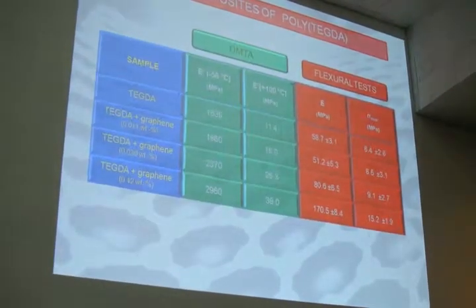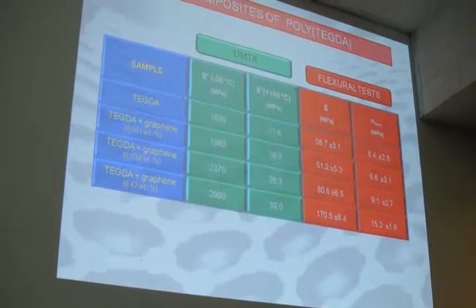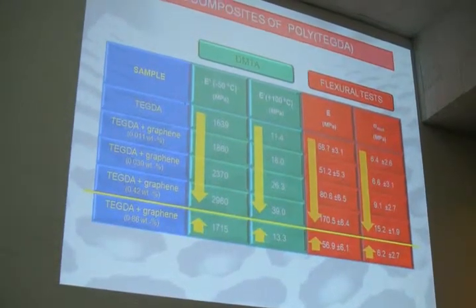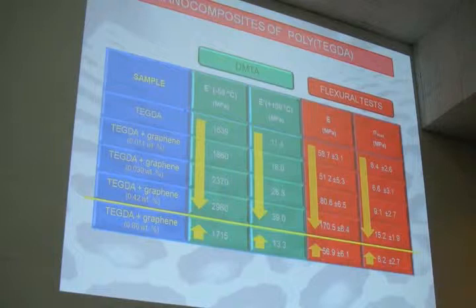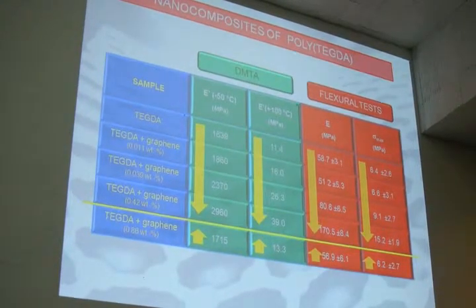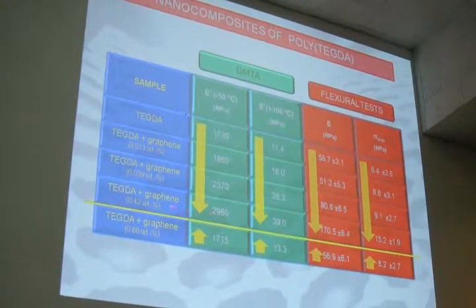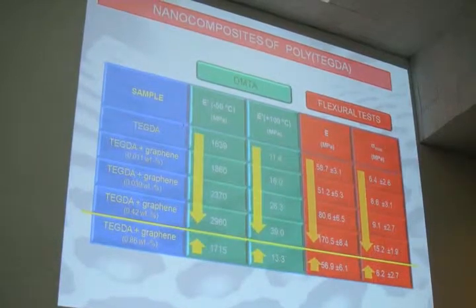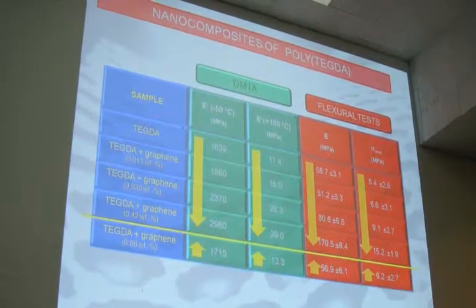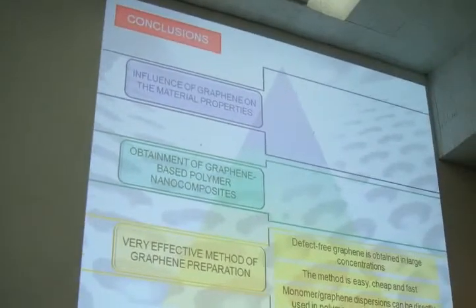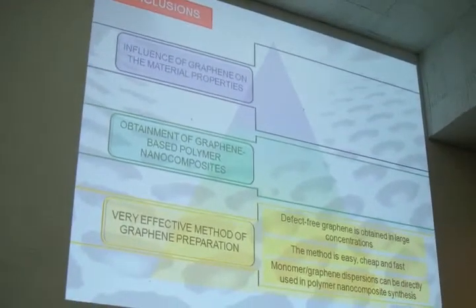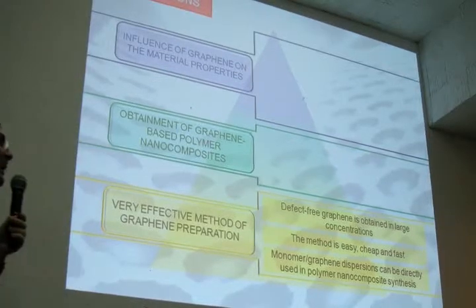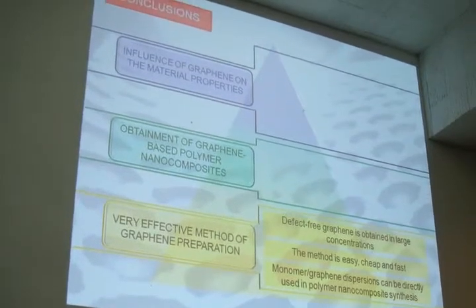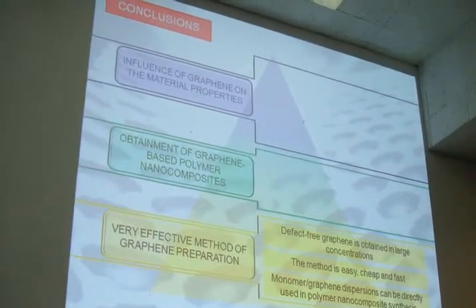And this is also confirmed by this other experiment about the mechanical properties, about the modulus. Again, we have an increase of the modulus up to the threshold value, and after that, a decrease of it. Okay. I don't know if it was too long, but I have finished. I just have to summarize what I said.